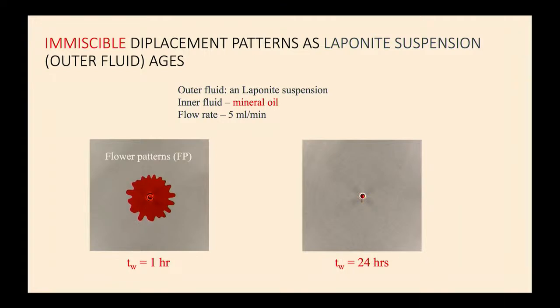Again, it's the same clay as before. All we've done is we've changed the miscibility of the two fluids at the interface. And then you wait much longer, and then again you introduce oil in a fresh sample. You can see it changes. That is because at 24 hours of age, the clay has many elastic structures, right? So as the oil propagates through these elastic structures, it has to break up these structures. So lots of elastic stresses are being released. There's a huge energy cost, and that is the reason why you find these ramified structures.